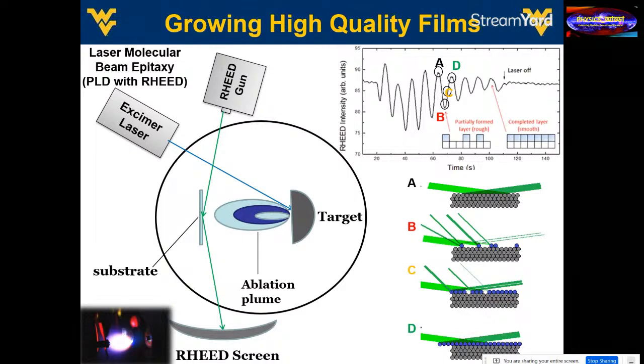And then as you start to grow, so you hit your laser on your target, and as atoms start to collect on the substrate, it's going to scatter some of this electron beam, right? So your intensity is going to go down. But if you are growing in such a manner that you aren't getting a bunch of clumping, but instead you are getting nice layer by layer growth, so it tries to fill in almost entirely. It doesn't have to be perfect, but it tries to fill in one layer before it goes to the next. If that happens, you once again end up with a nice smooth layer. And so you're going to get good intensity off your electron beam.